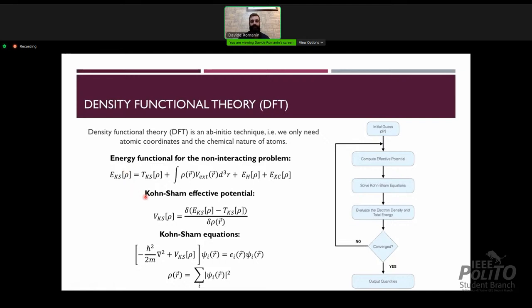And moreover, in the Kohn-Sham approximation, we map the difficult many-body interacting problem into a simpler non-interacting one, where all the difficult many-body interactions are put inside an ad hoc functional, which is called exchange correlation functional, which is chosen depending on the material and on what we have to simulate. After that, we just need to solve the Kohn-Sham equations in a self-consistent way in order to reach the minimum of this energy functional and retrieve the ground state electronic density, from which we can extrapolate the equilibrium properties of our system. Moreover, this technique is called ab initio because the only ingredients that we need are the crystallographic and chemical information of our system and of the elements that compose the material.